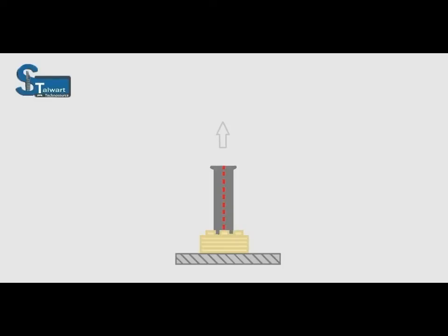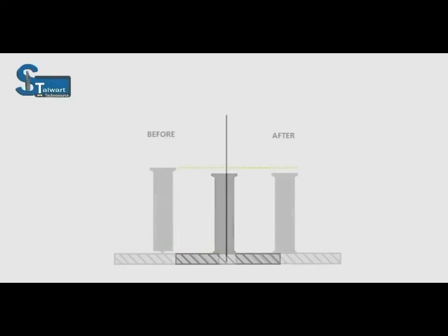The stud is lifted from the workpiece for a prescribed length by the solenoid in the gun. It's held for a prescribed length of time. At the end of the weld cycle, the stud is released, and plunges into the molten pool of the workpiece contained by the ceramic ferrule. The gun is lifted off from the welded stud. The weld that results is that the length of the stud is reduced.